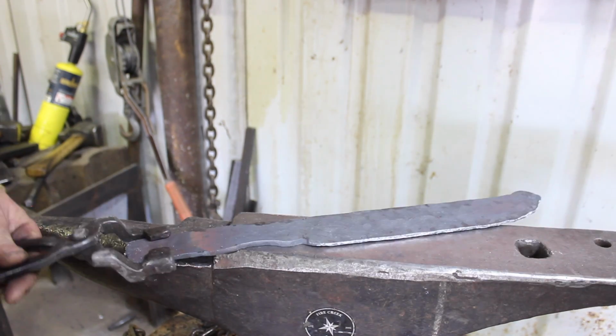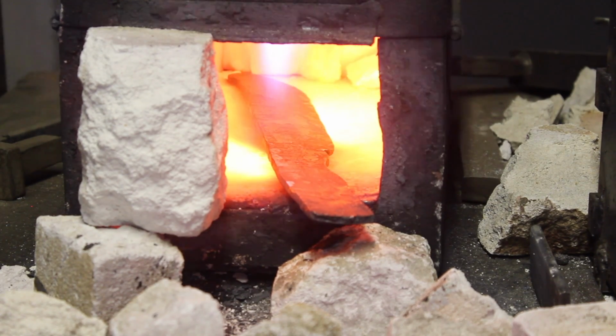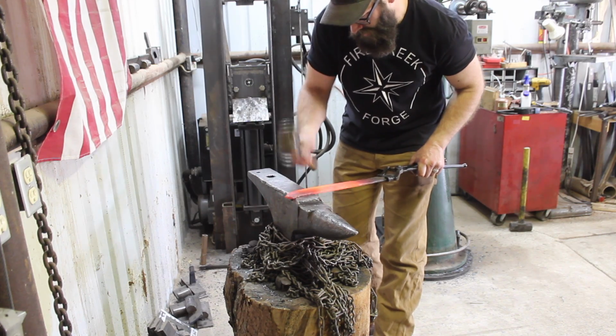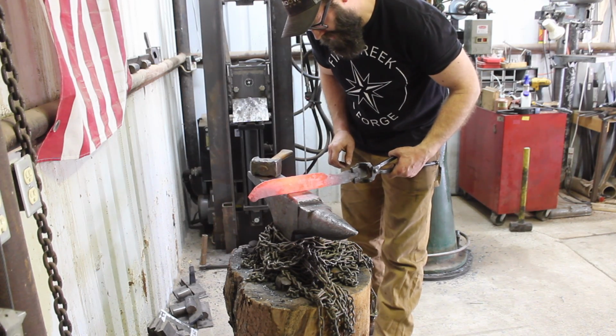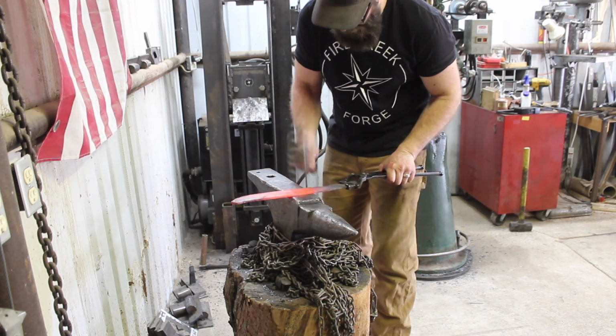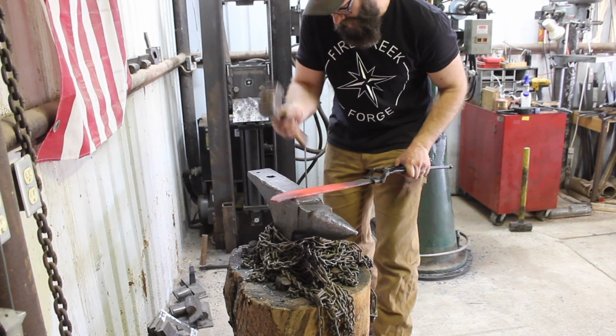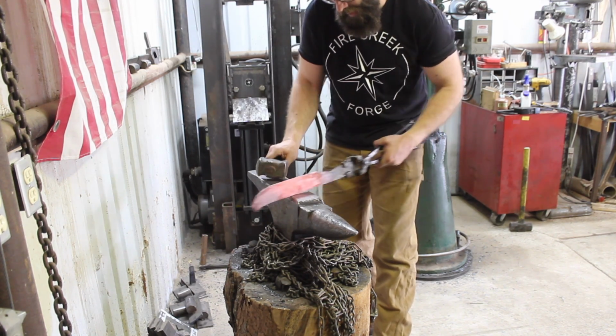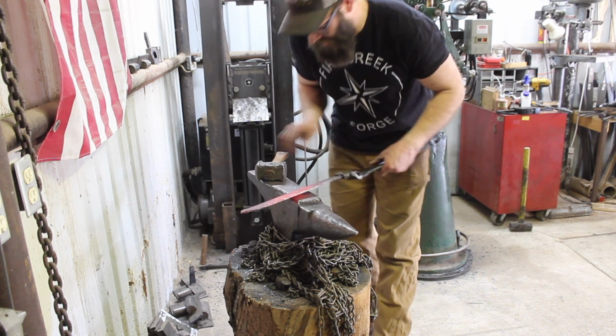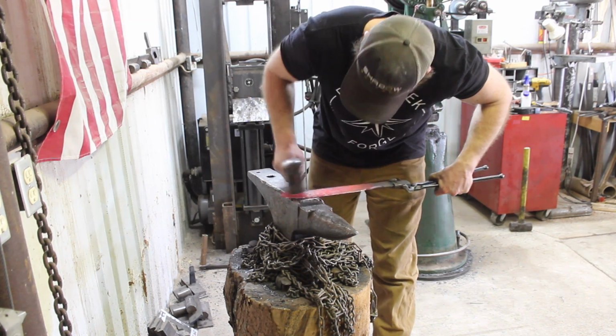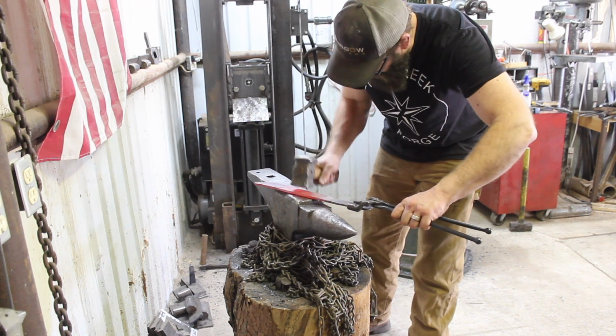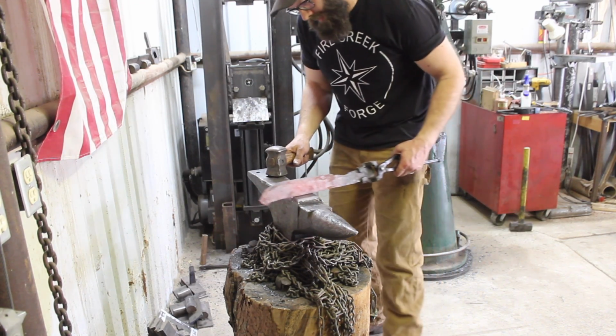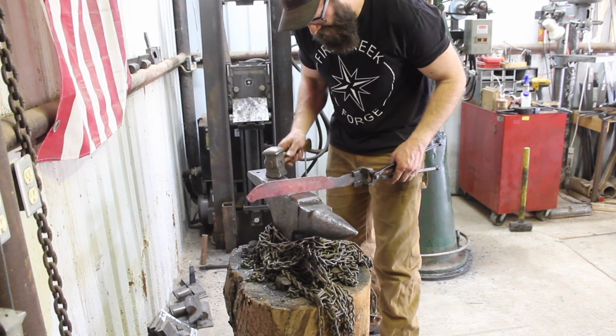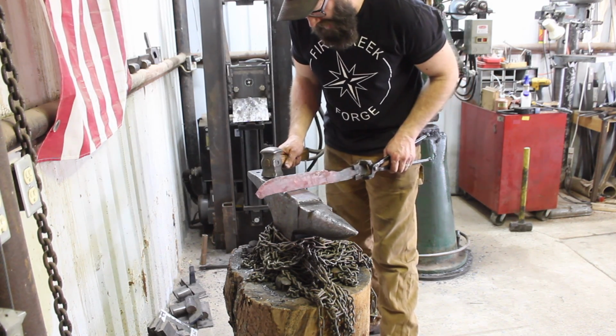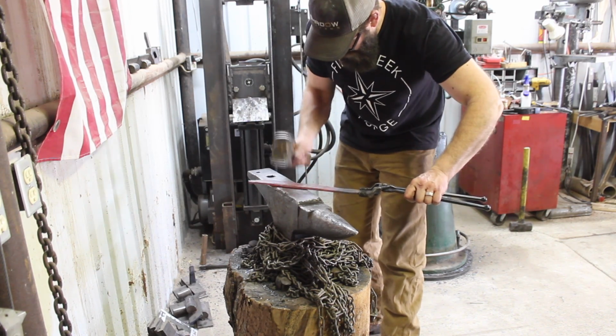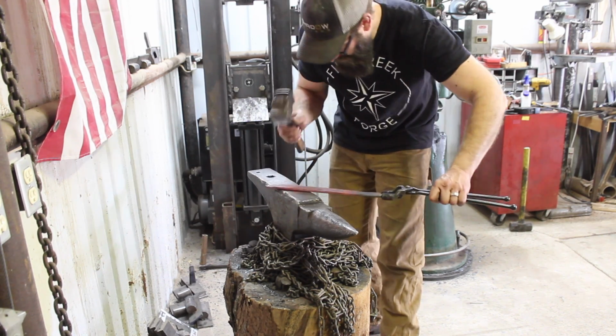Oh, but I forgot. As I was checking my final straightening, I realized that my bevel was a little bit off center, and normally it wouldn't be enough to worry about too much. You could correct it with grinding in the final project and not even have a problem. But in this case, because we're doing a San Mai construction, we need to make sure that we forged it as close to center as possible, so that when we go to finish our blade, we don't have an offset or out of center edge steel giving us an uneven reveal on each side of the blade.